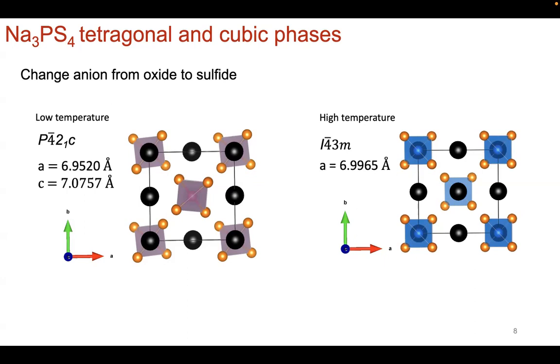Now, the difference is at lower temperature, Na3PS4 has this tetragonal P-bar4 2C type structure. And what you see here is the lattice parameters: A is 6.952 angstrom, C is a little bit larger, it's 7.0757 angstrom. And you can see that the tetrahedra are a little bit skewed. The sodium ions are in black and they're sitting in front of these tetrahedra of PS4. But you can see it's a little bit tilted. And that's the phosphorus in pink there.